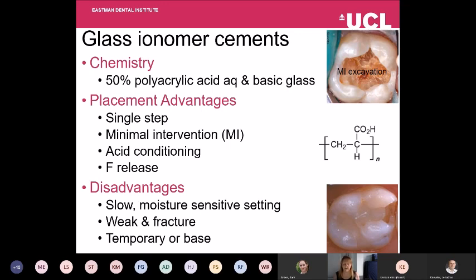Glass ionomer cement is often composed of a 50% polyacrylic acid solution, an aqueous solution. Polyacrylic acid has a carboxylic acid group that is reactive with both the tooth structure and also a glass that is combined with the cement.